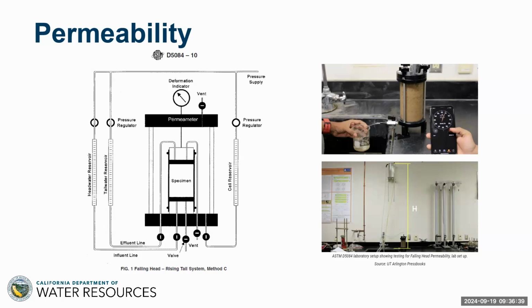So I think most people on the call here will know what permeability is. It's just an index of how water moves through a solid. For example, if we have a sand, the measure might be 10 to the minus 3 centimeters per second. If it was clay, it might be 10 to the minus 6 centimeters per second. And what we're looking for in a really nice grout is something that is maybe 10 to the minus 9 or even less. And that's perfectly achievable using the right blend of materials and equipment.